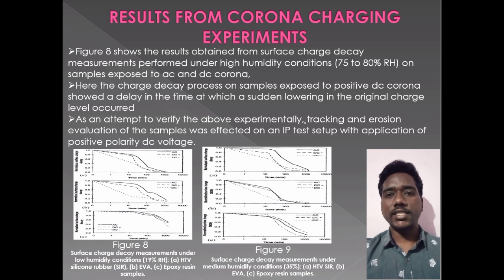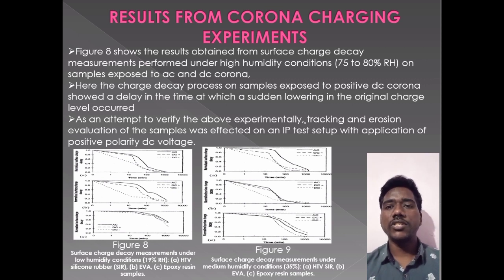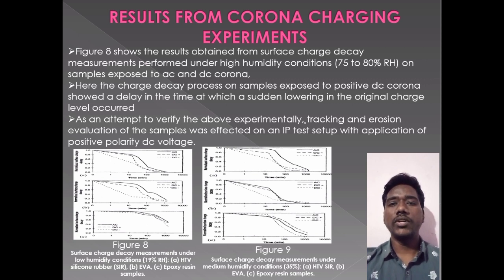Based on the discharge characteristics of both AC and DC corona, it can be said that in the AC case, surface charge buildup is due to an injection mechanism, whereas charge buildup due to dipole orientation is believed to have occurred in samples exposed to DC corona. High frequency electrical discharges of streamer type were observed with AC voltage application. Pulsating glow type corona was observed on the DC energized setup. Slightly longer charge decay times were identified in measurements made at the lowest humidity level.